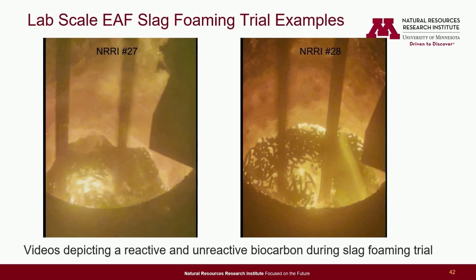So when I play them, this is a video of our slag foaming test. So one sample is going to perform really well. You're going to see it foam. The other sample, it's going to not react at all. And so this really showed us that the formulation does matter. All those parameters that we played around with make a difference. And so you can't just throw any biocarbon biochar in for an injection carbon and have it work.